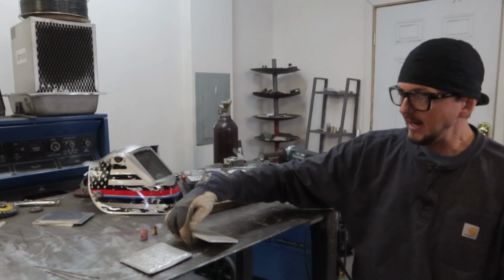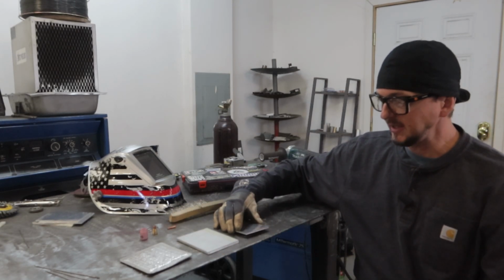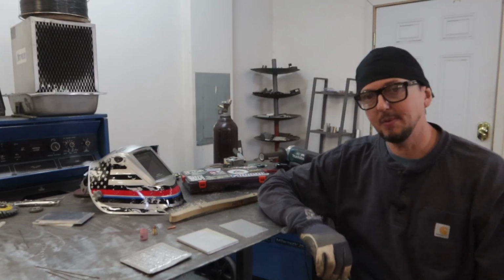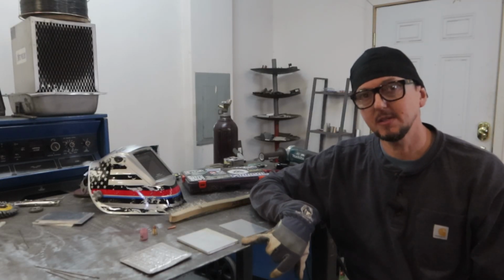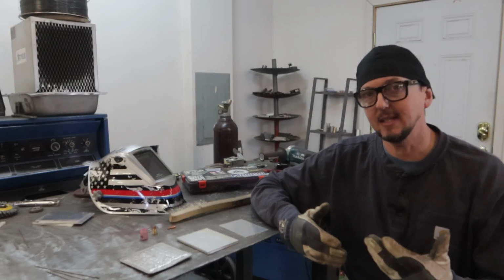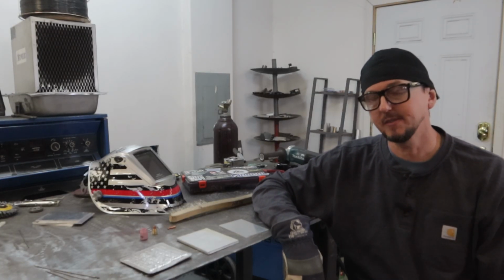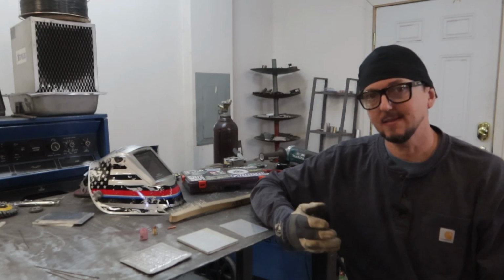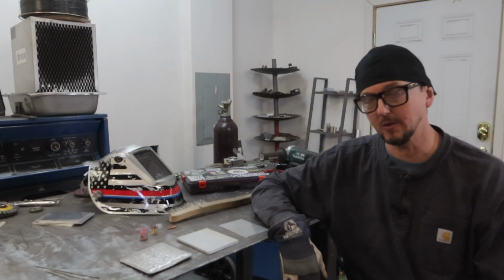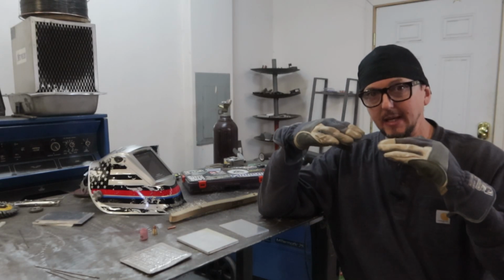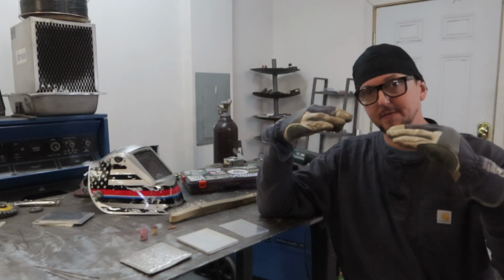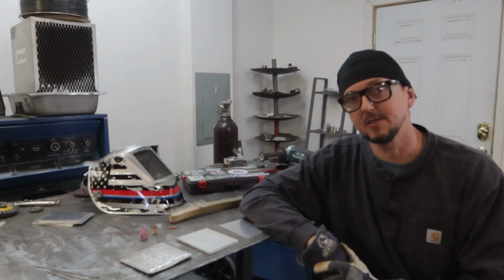Okay, so the first thing that we need to do is clean this oxide layer. As I said before, the oxide layer builds up over time. When this aluminum is produced, immediately when it is subjected to the atmospheric air, it starts to build up this oxide layer. The oxide layer has a higher melting point than the base material. It has a melting point of about 3,600 degrees, where the base material of the aluminum actually melts at 1,200 degrees. So if we just try to weld it without breaking up that oxide layer first, that top layer will not melt, and it'll just start to move around on the surface because the bottom layer, the base material, is starting to melt underneath.